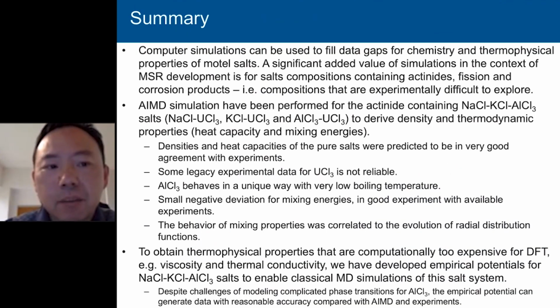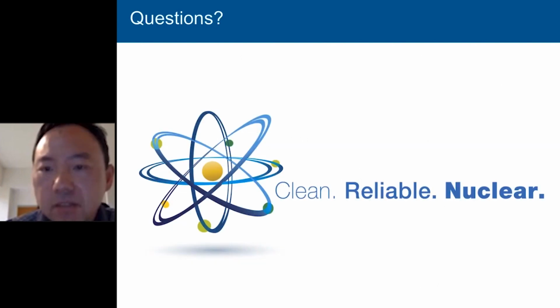So now I'm going to the summary. Again, as I mentioned, computer simulation can be used to fill the data gaps, and this is very, very important, especially for salt compositions containing actinides, fission and corrosion products. These kinds of compositions are experimentally very difficult to explore. This is where the simulations are extremely important. Here are some of the summaries, which I'm not going to go over. And finally, I want to mention that there are still some challenges in modeling the complicated phase transition of aluminum chloride. This gives us some discrepancy between the modeling and the experiments. So that's the end of my talk.